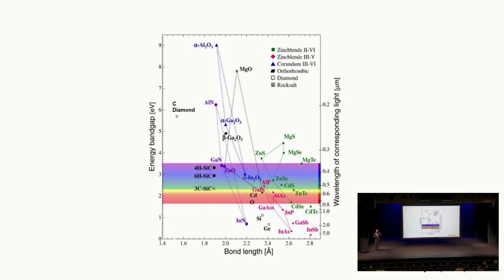That's not an easy experiment to do. We've demonstrated that you can get a strain of 9% in tension, maybe 13% in compression. We can do finite element simulations and show that when it fails at 9%, that's very close to the theoretical strength of diamond. That we have demonstrated. But how do we demonstrate band gap change, especially when it's localized and highly graded, not uniform? So we decided to do density functional theory calculations.